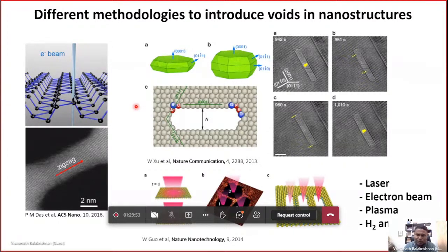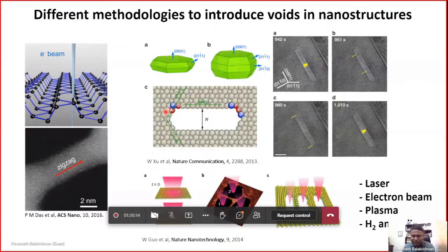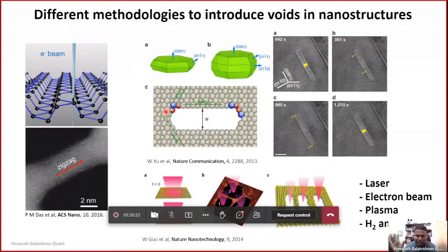So as long as your threshold voltage is sufficient to knock out the sulfur, of course tungsten would be much more difficult. At least if you are able to remove sulfur, then definitely it can be done with the E-beam as well. TEM is relatively easy because TEM is operated at around 200 kV, 300 kV. In some cases, if you want to avoid defects, people also use low kV TEM. But yes, as long as you are able to match the threshold, it should be possible, not only with the E-beam, even with other techniques.